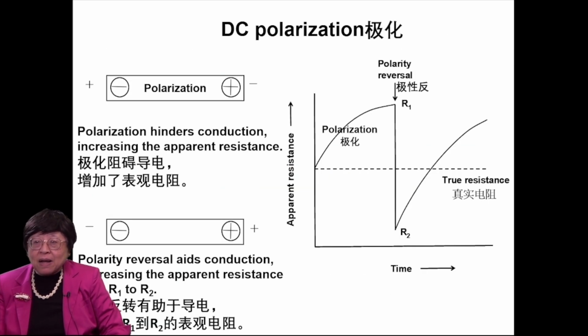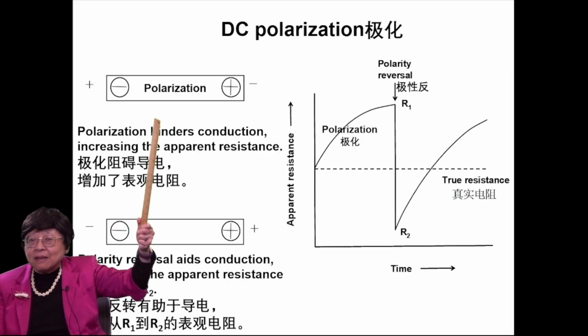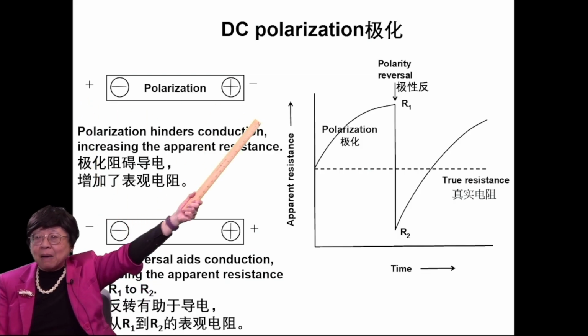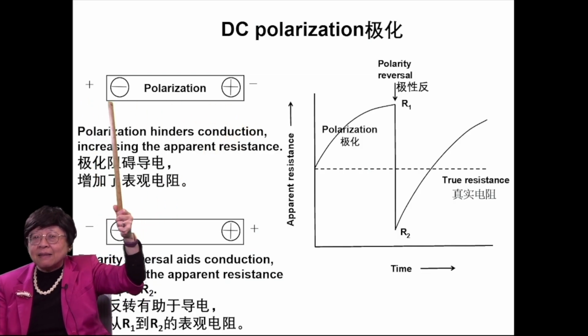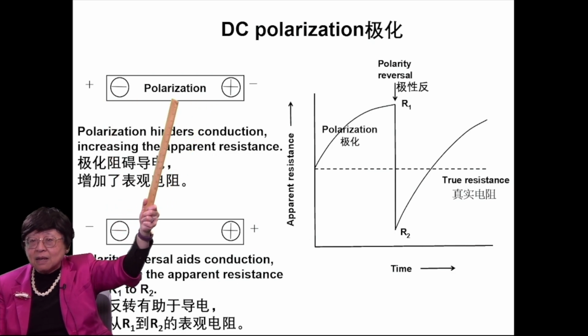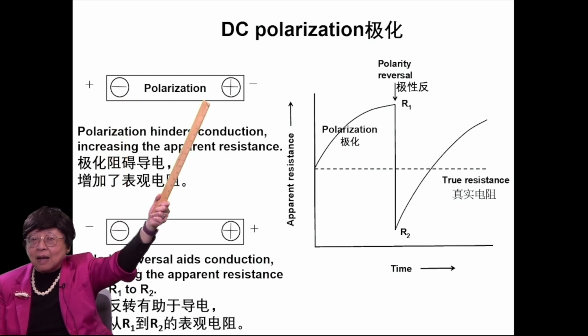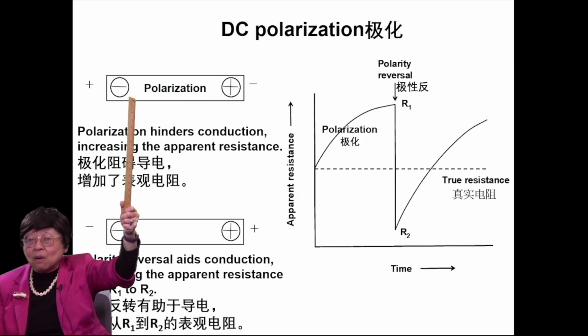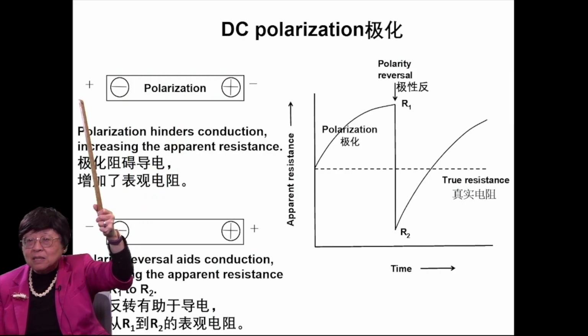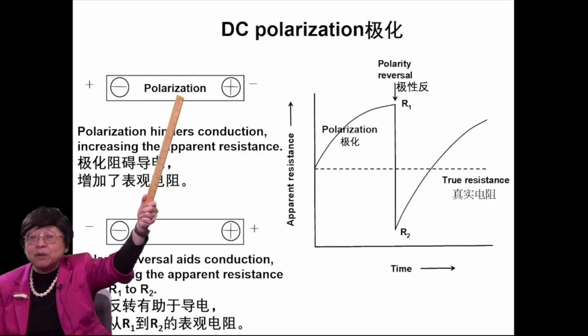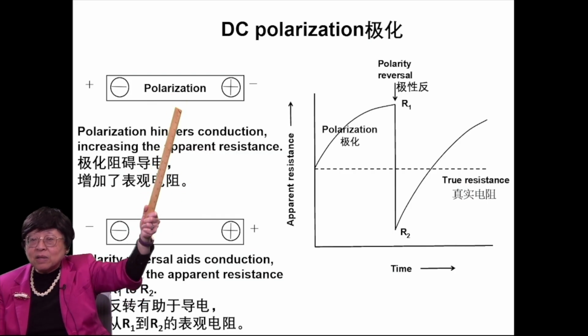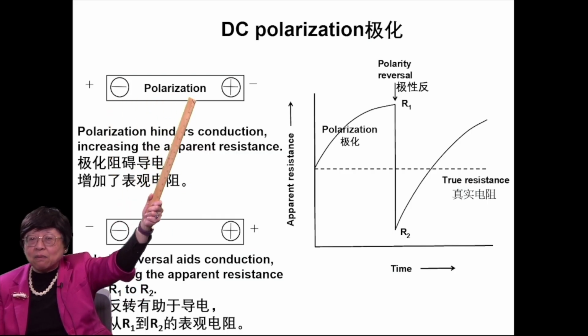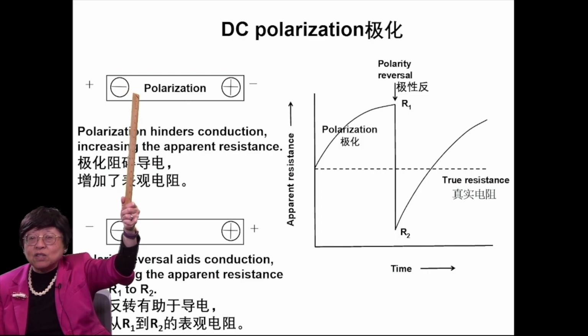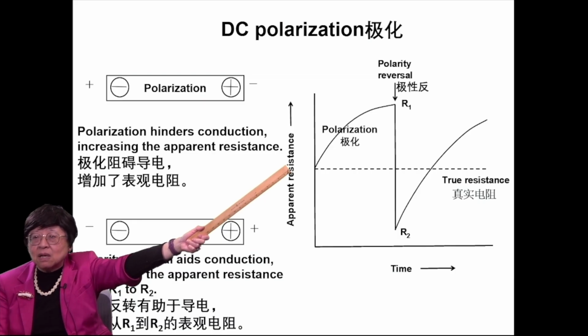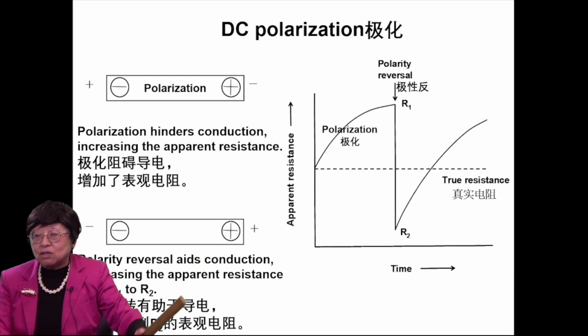One can have polarization under DC. This is plus and minus, the DC applied voltage, and that causes the polarization. The plus sucks the minus. And so as you apply the DC voltage, the polarization builds up. And note that this polarization causes a voltage which opposes conduction. As a result, the apparent resistance goes up as the polarization builds up.